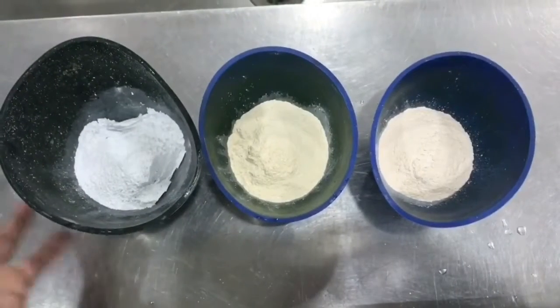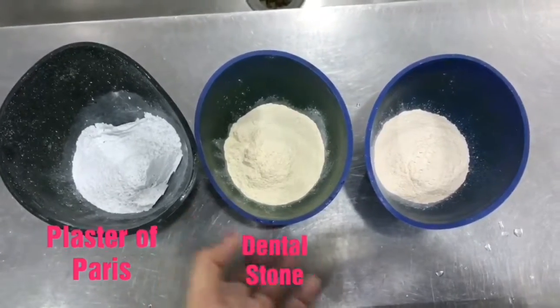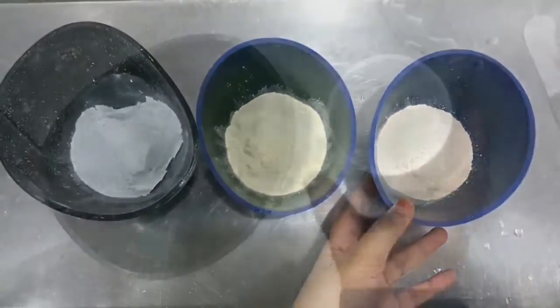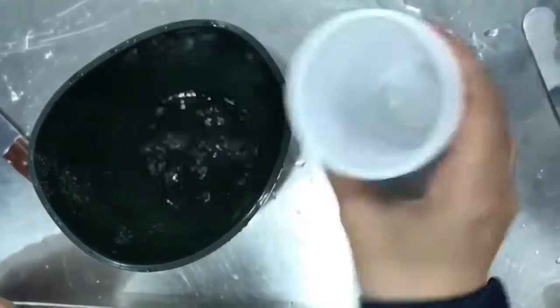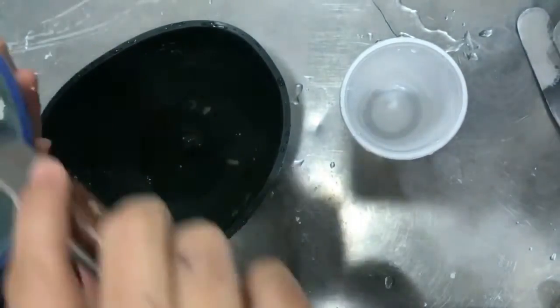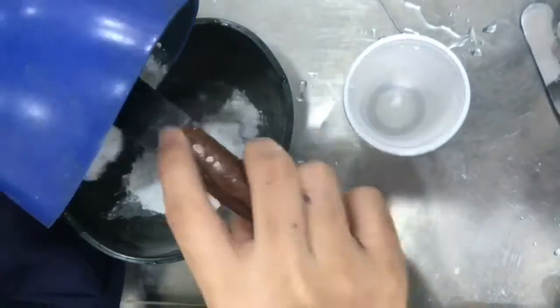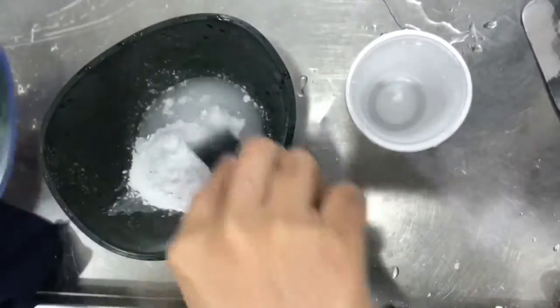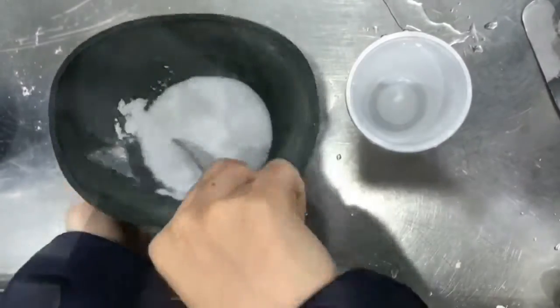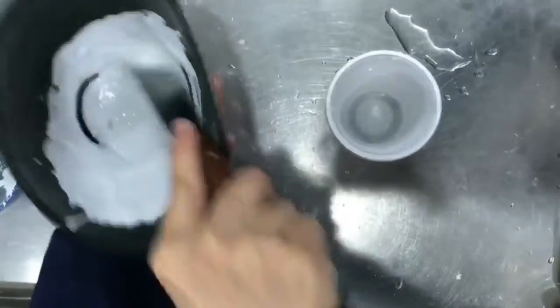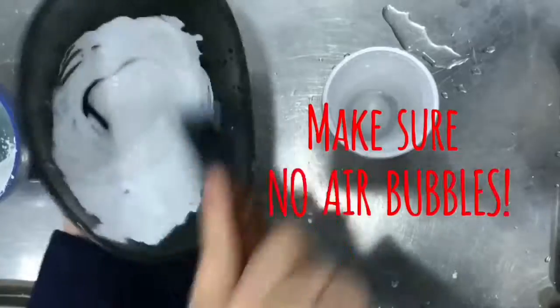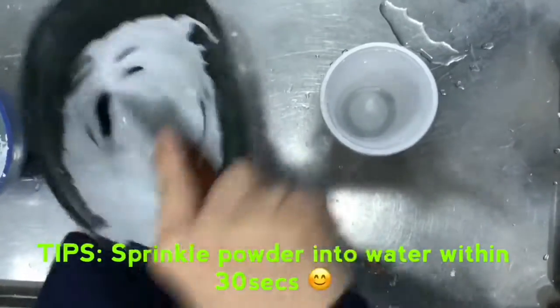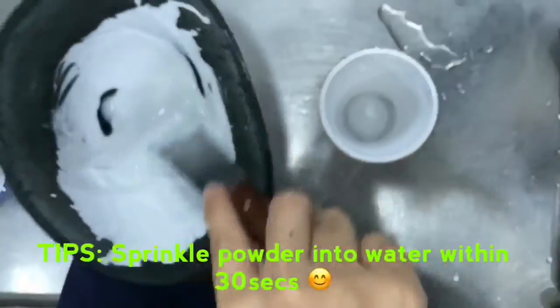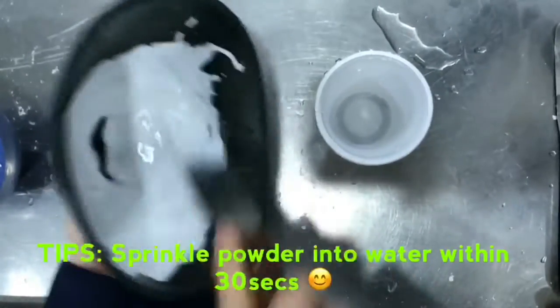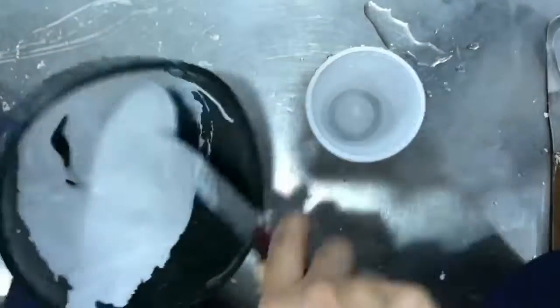In today's demonstration, we're going to use plaster of Paris, dental stone, and dental stone with high strength, low expansion. For plaster of Paris, the first step is we pour the water inside the bowl and we put the plaster of Paris in, and we mix the powder and water together using the spatula thoroughly to make sure that there's no air bubble. For a better result, we need to sprinkle the powder into the water within 30 seconds to allow any air trapped within the powder to escape, and it will reduce the bubbles in the final mix.